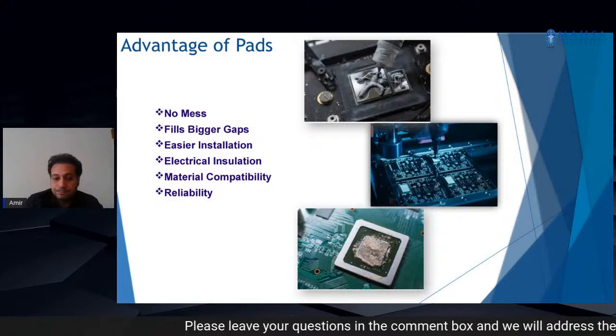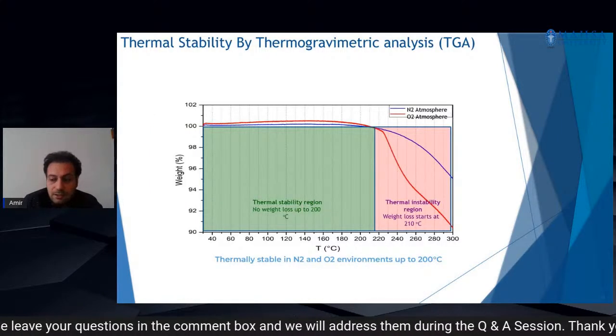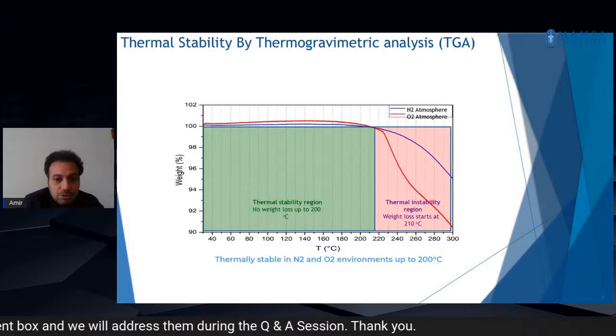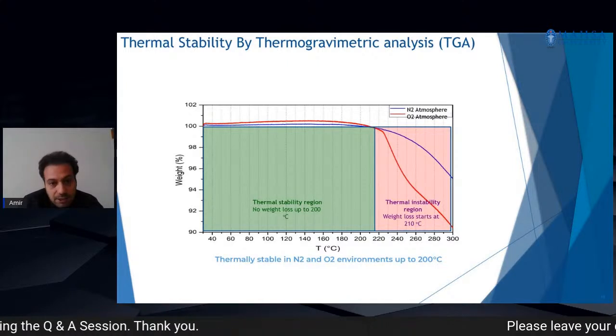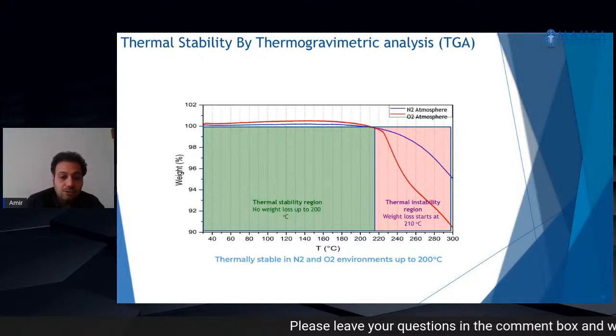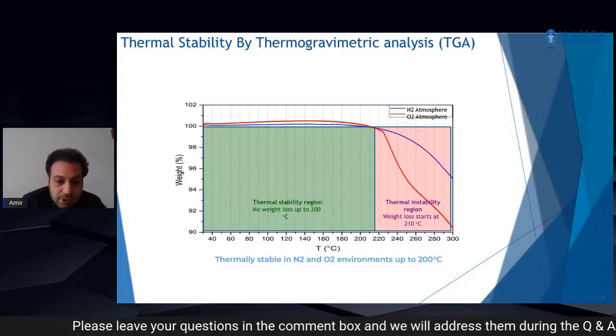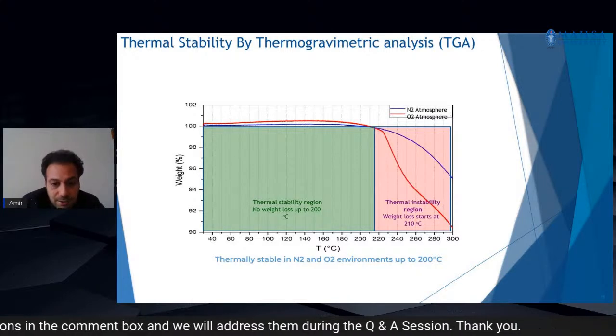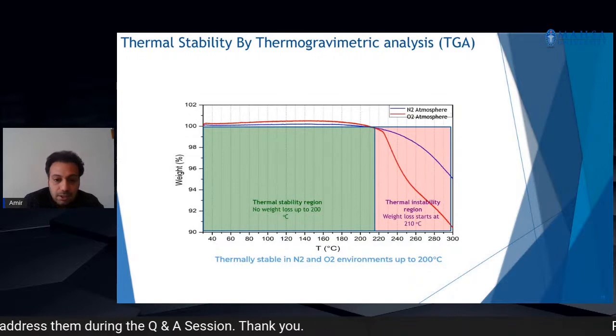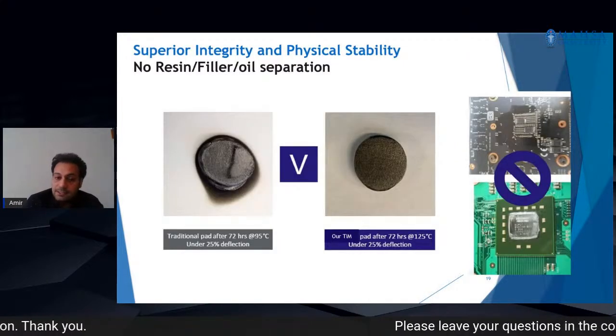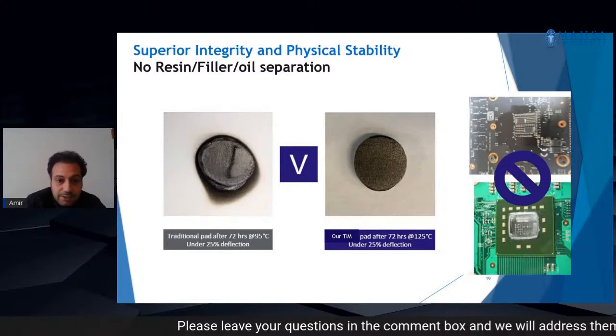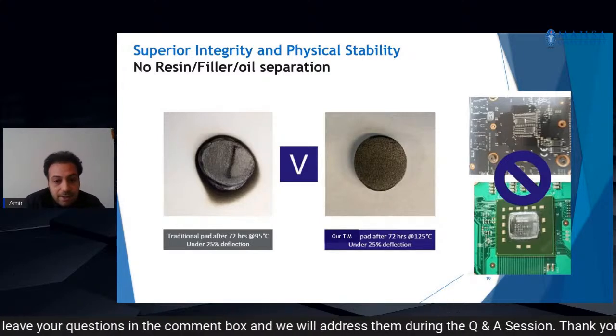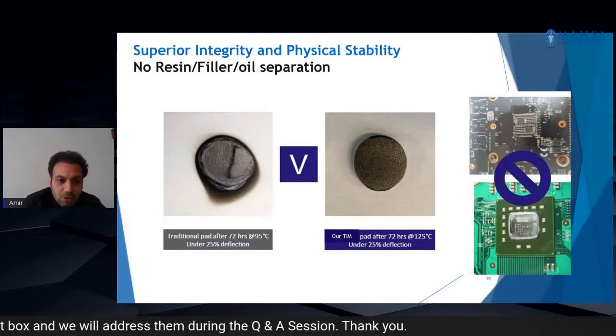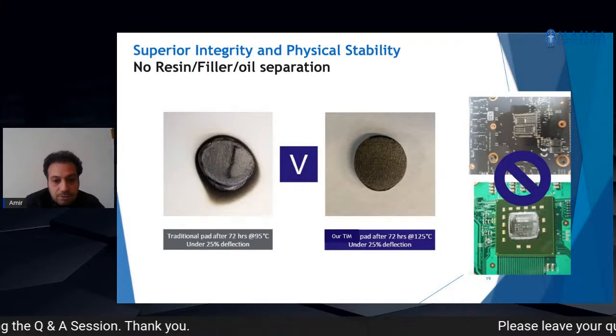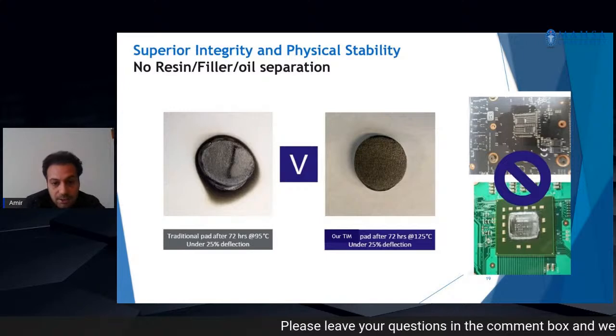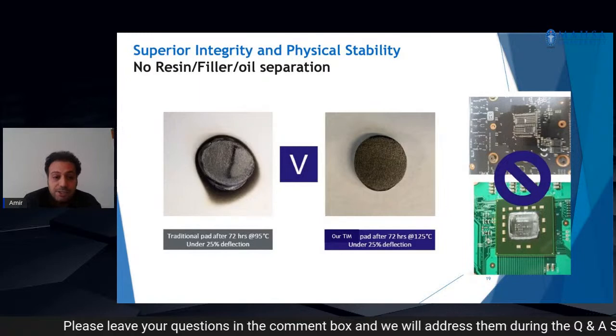Here, just to show how stable our sample is, we analyzed with thermogravimetric analysis, TGA, showing that our material film is stable at high temperature. As you can see, it goes up to 200. And also here we are showing the stability of the sample: you can see without any resin and oil separation, our thin pad, after long hours at temperatures over 100, is still uniform and without any damage on the surface. That is clear in real application, where damage to our systems matters.